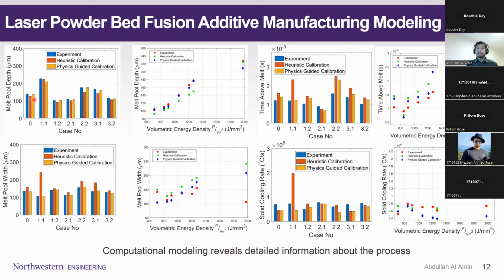The red one is the first type of simulation that I have done. This is using a heuristic calibration. I'm not going into too much detail about what the heuristic calibration is, but it is a method to approximate the amount of energy that is going into the system to model the additive manufacturing process. The second one is similar to the first, but it relies mostly on data. So I am trying to analyze some of the literature data to come up with a more uniform, more accurate heat source model so that we can have a better prediction of the melt pool depth. And that's what I'm plotting over there and trying to compare.